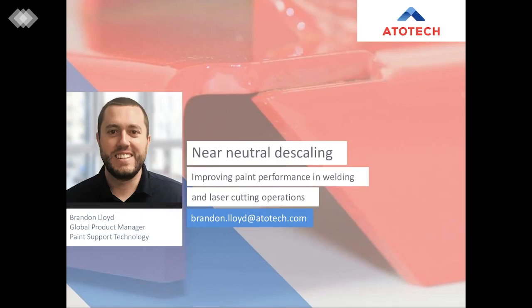What pH range do these products operate at? Sure. Typically at operating concentration, these products, being Uniprep ACD 105 for immersion applications and the ACS 100 for spray applications, operate around a pH of about 4.5 to 5.5.